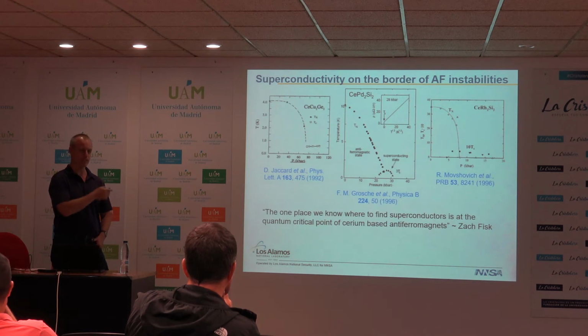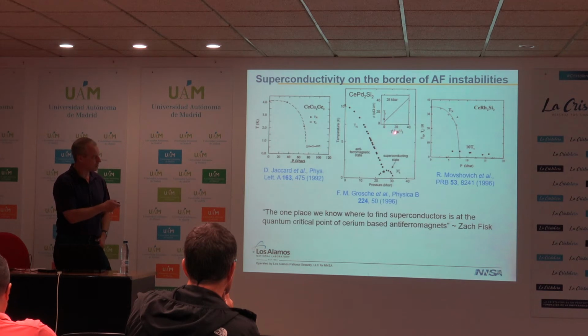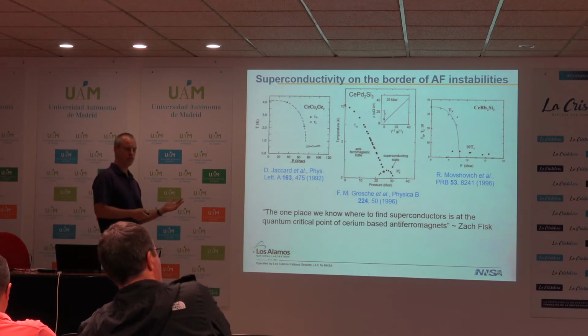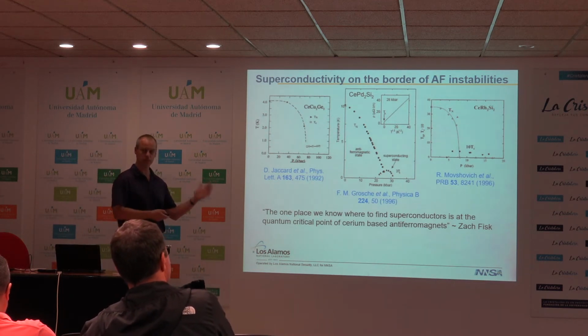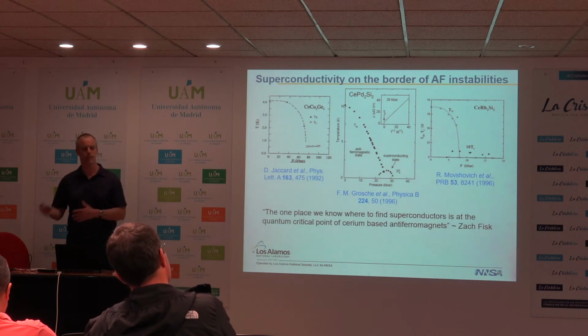So if you get a clean cerium antiferromagnet, drive the magnetic transition to T = 0. It's a second order phase transition generically. You get quantum critical behavior. So you see here the resistivity as a function of T. In this case, this is T to the 1.2. You get this linear behavior. So you get some sort of power law. The power law is actually not universal. We don't always see T linear. So some systems see T linear. Others see T to the 3/2.